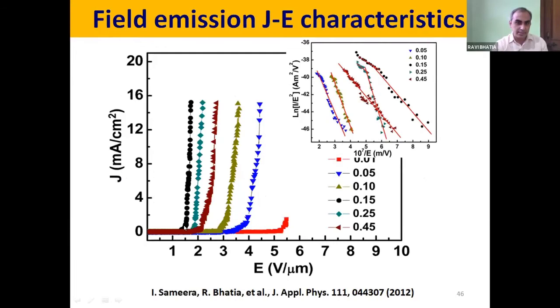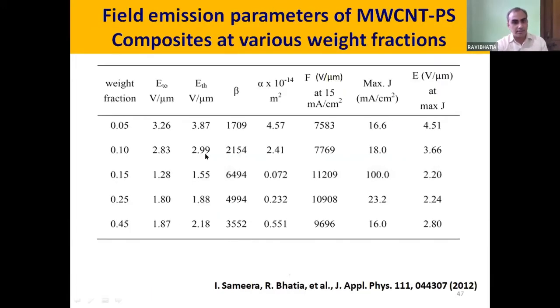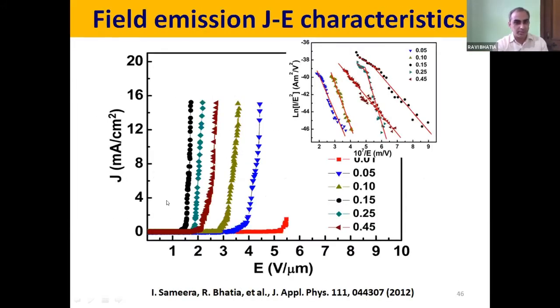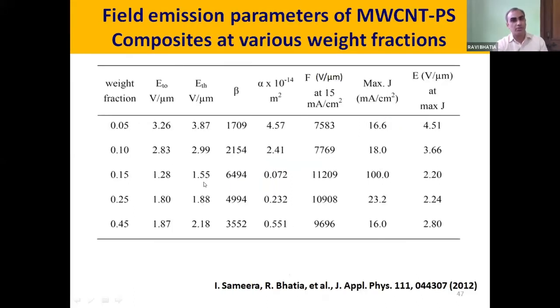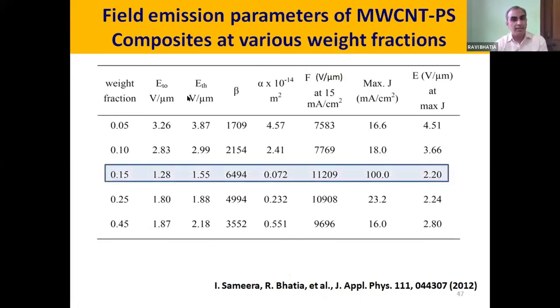Turn-on means where the current starts increasing more, and the other value that is called threshold is at a particular value. For example, at 5 or 10 milliamp per centimeter square, that particular voltage is called threshold voltage. And interestingly enough, the beta value, which I already told you is called the field enhancement factor, is found to be the highest for this particular sample, 6494. So beta is more in the case of the 15 weight% sample, which probably can explain the result, but still